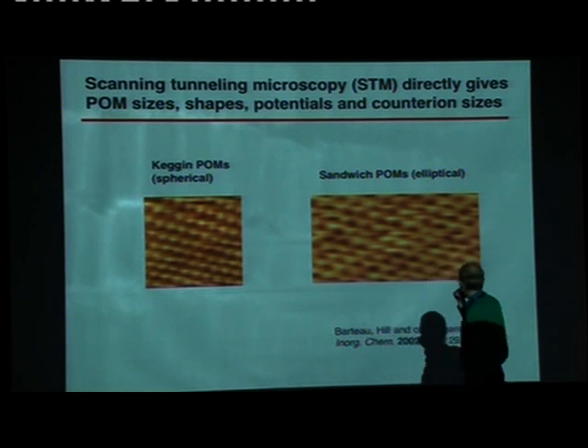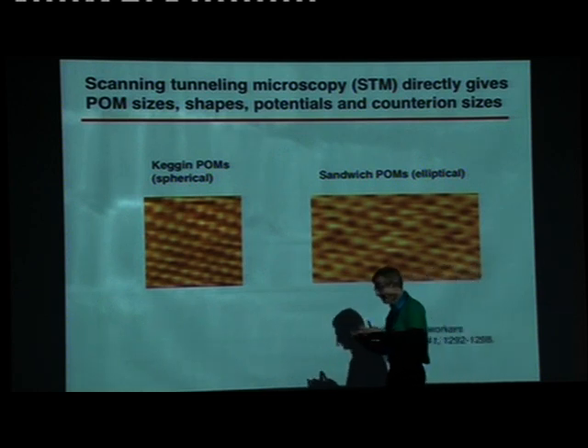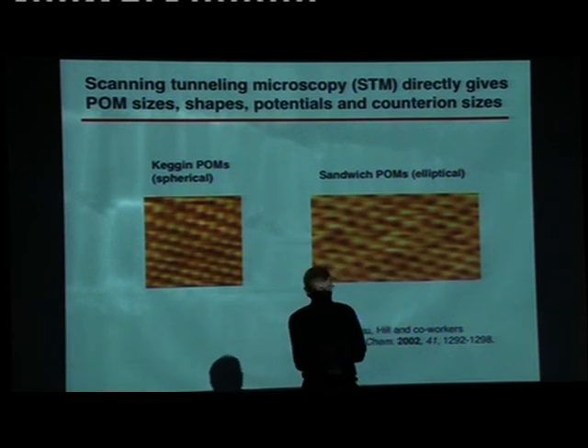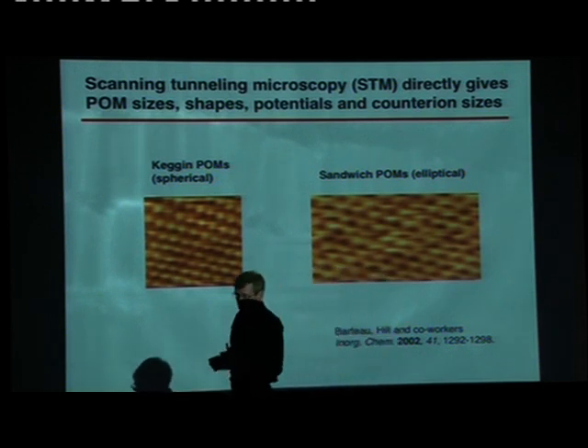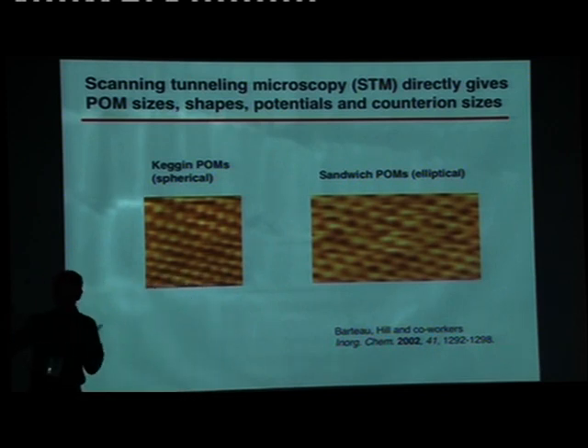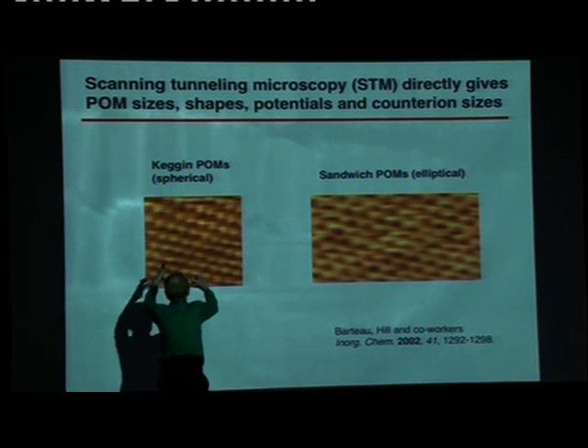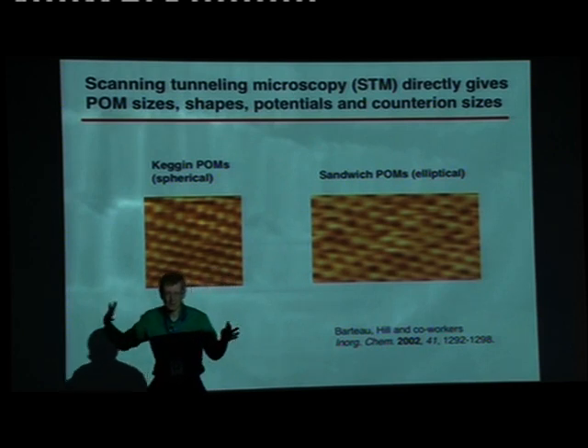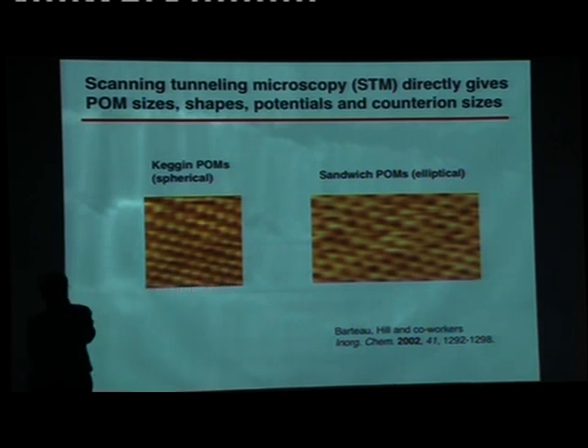And the nice thing about this is that, again, the POMs have high charges, so you can change the cation. You can have a small cation like sodium. It'll probably be hydrated, so sodium with 5, 6, or 7 waters. And you can go to something really humongous, big, like tetraheptylammonium, nitrogen with 4 heptyl groups on it. And what will happen is that these corrugations, these spacings, will go out as the cations push out the anions. And there's some reversibility to this.